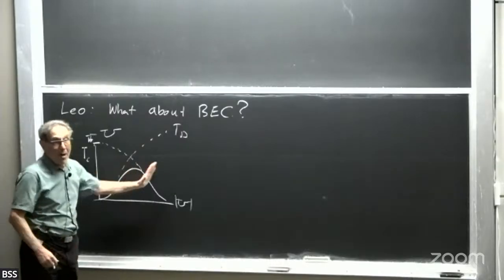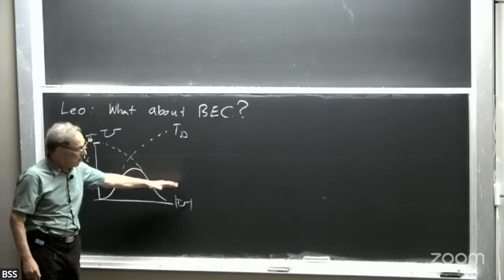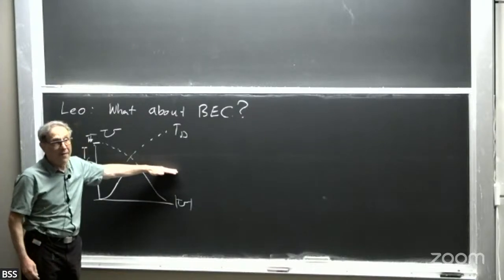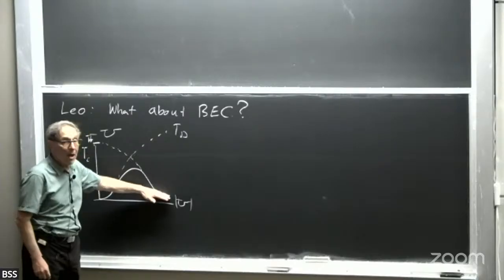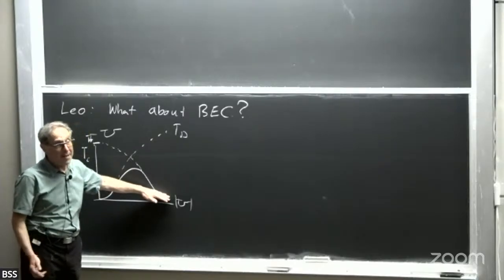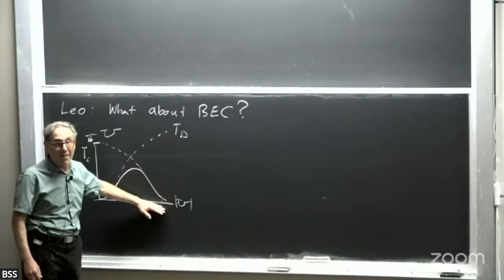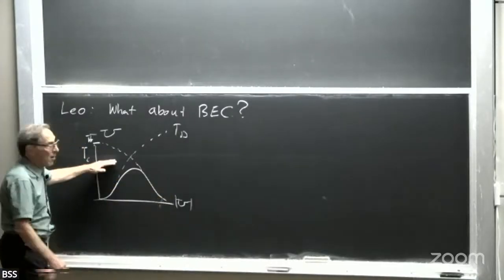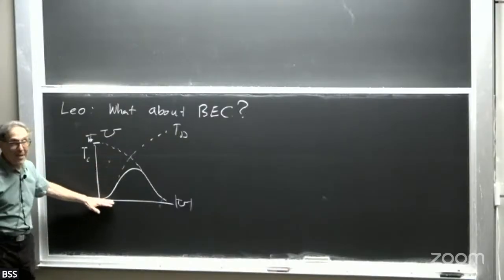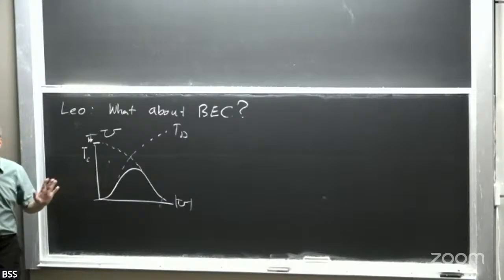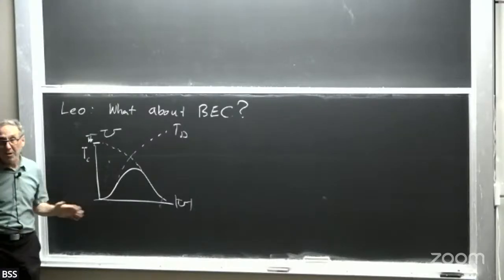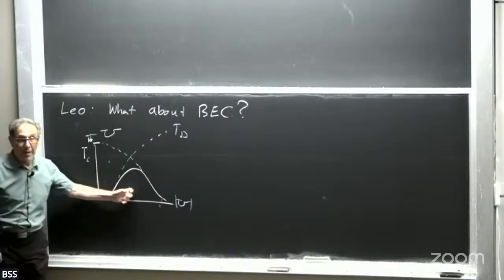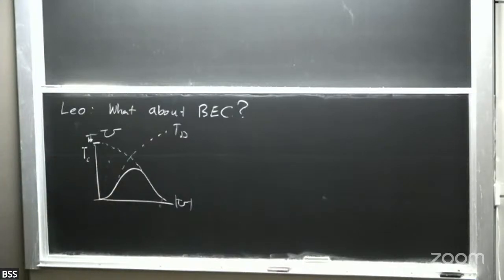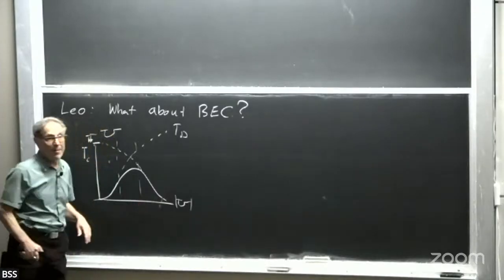This crossover, oh, and by the way, this is a good example of a crossover. Here, this normal state should be thought of as the normal state of classical charge 2e particles. And at low temperatures, these classical charge 2e particles become quantum mechanical and Bose condense. Over here, we have a Fermi liquid and we have a BCS description. These are totally different descriptions of the system, different degrees of freedom. On the other hand, the superconducting phase is one phase. There's no phase transition separating them. So it's a good description, and there's this intermediate regime that's very hard to describe.